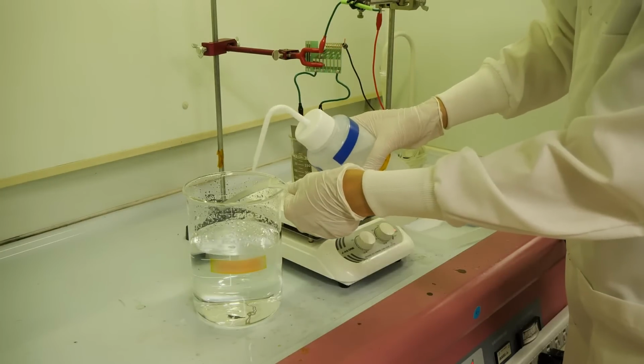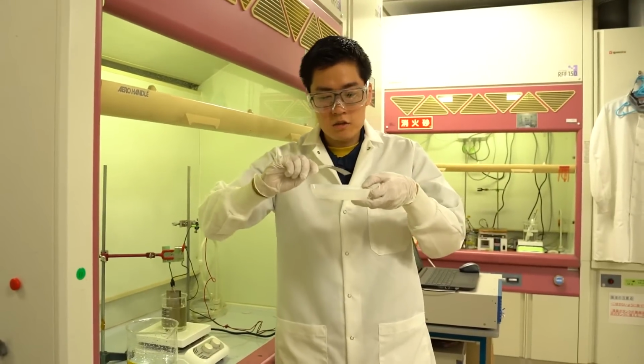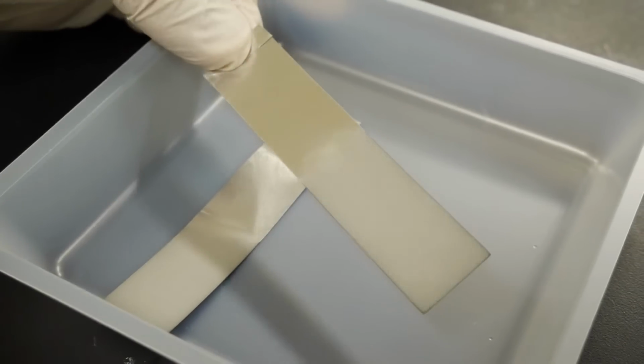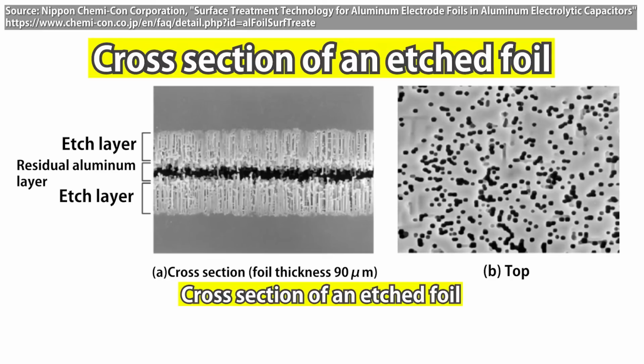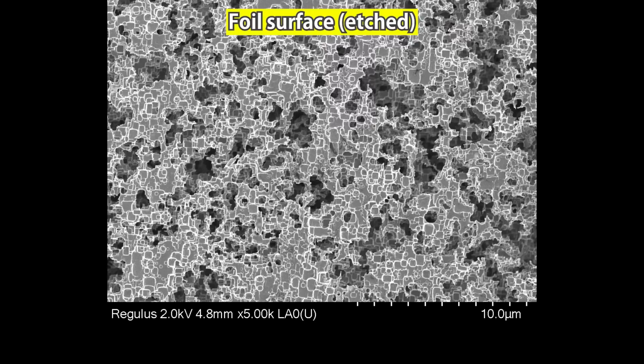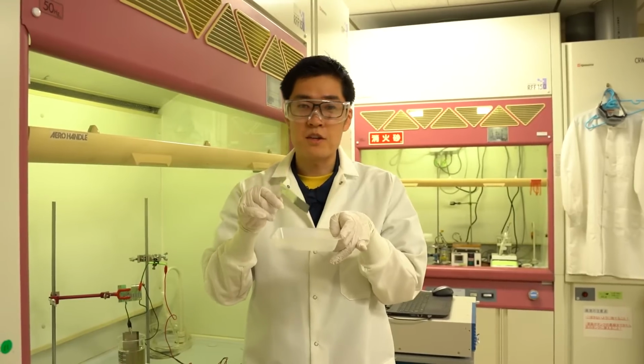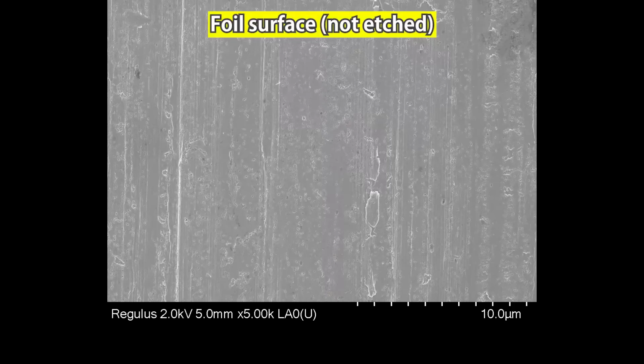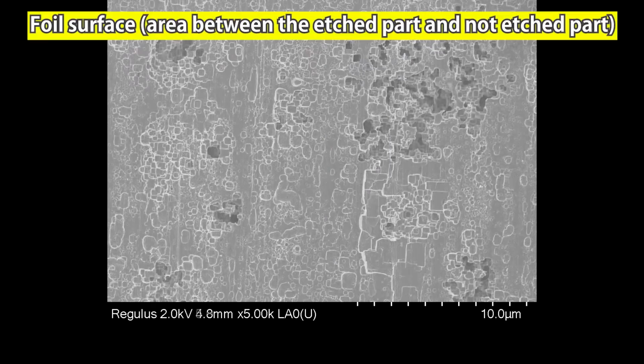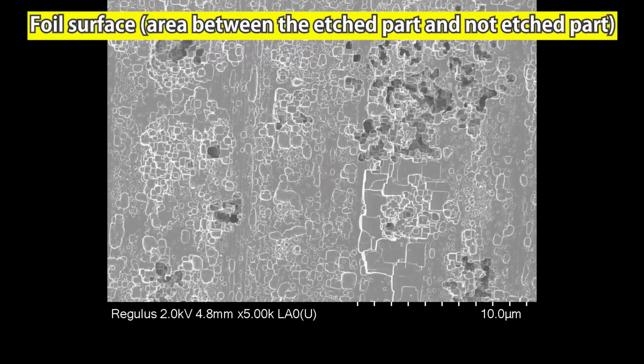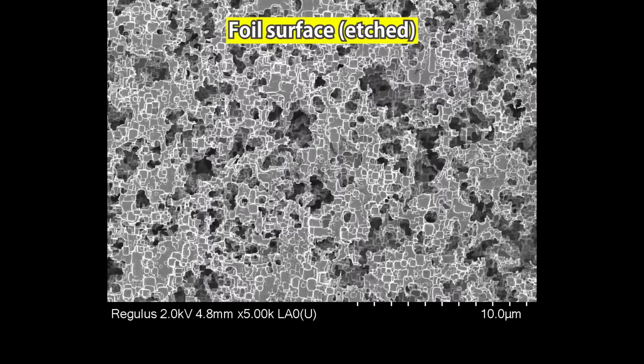Then, wash it. Because it went through the etching process, the foil lost its shine. The surface looks a bit rough. If you see the surface using a microscope, you can see fine pits on the surface of the foil. By filling these pits with electrolyte, you can make the best of the large surface area. This is the surface image of the aluminum foil I etched. The foil surface was smooth before the etching process, but after the process, there are many pits on the surface.